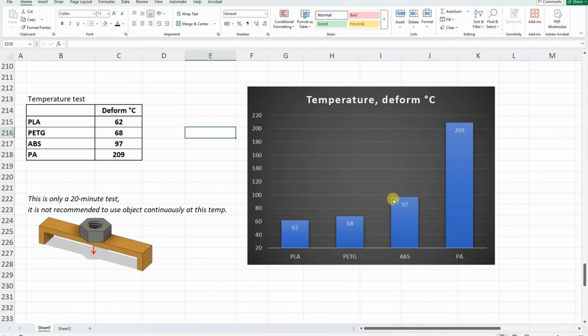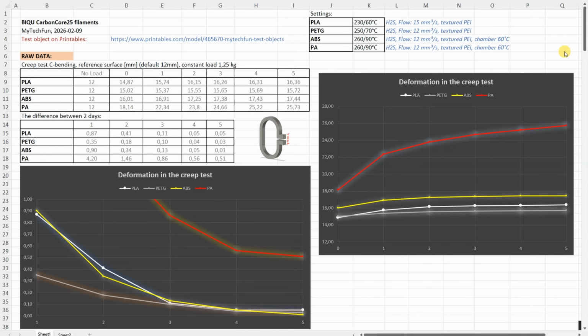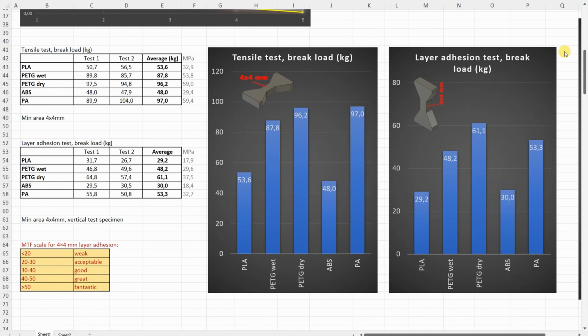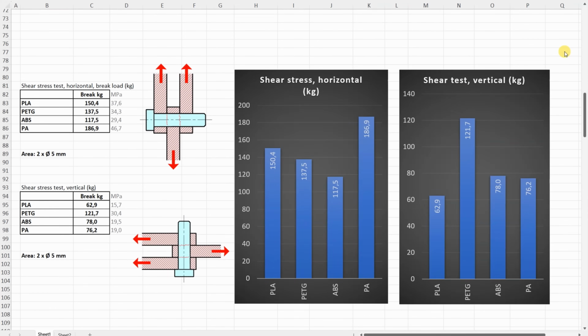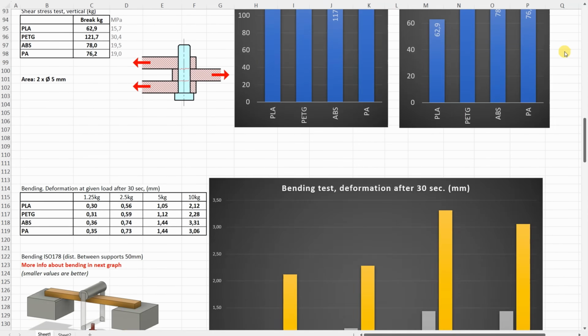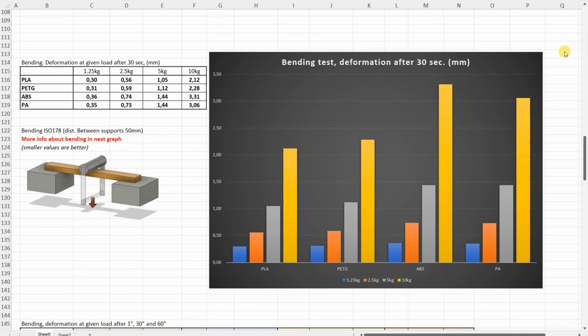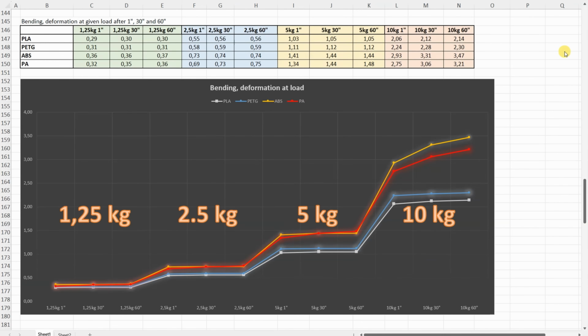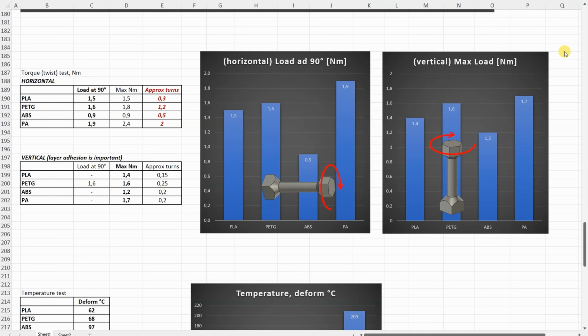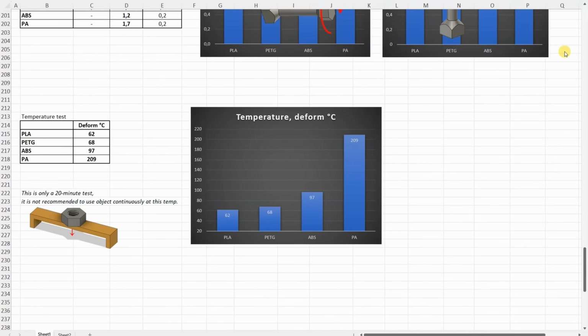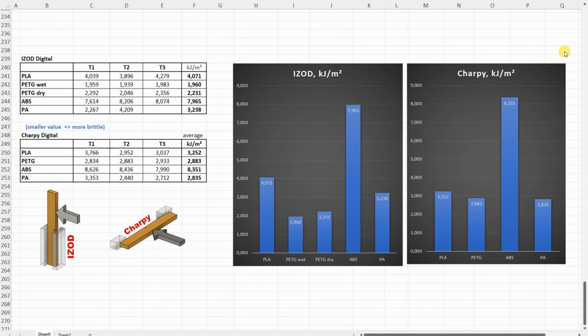And thanks to the fibers, in every case the temperature is a little bit higher than with the average base material. Our results one more time: creep test, tensile and layer adhesion, shear test horizontal and vertical, bending test to deformation after 30 seconds, bending test deformation after 1, 30 and 60 seconds under these loads, torsion test horizontal vertical, temperature test, and the impact tests, IZOD and Charpy. Just very quick conclusions, because this video starts to be too long.